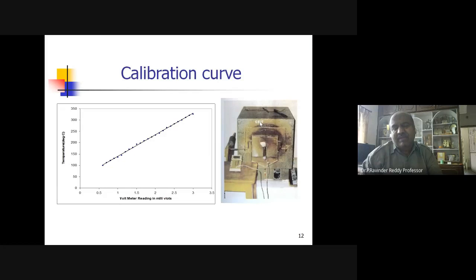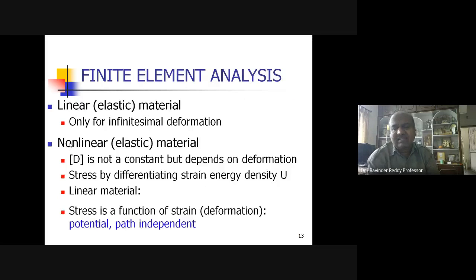And we need to calibrate, so we have an oven and keep the setup in it, change the temperature and measure the voltmeter reading. Then you will know the scaling, and you can convert based on the temperature which we obtain, and then get the true temperatures that we can get on the tool.